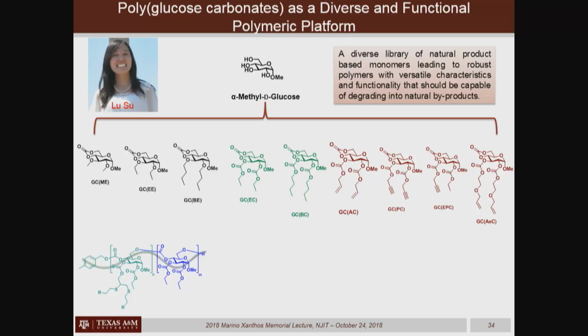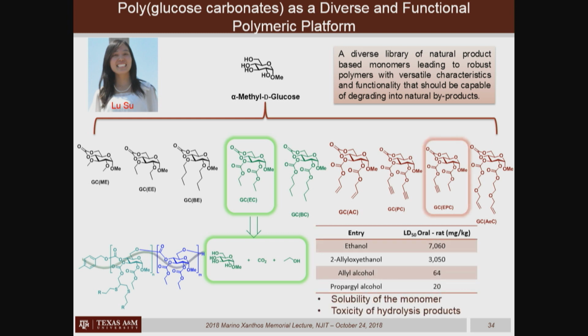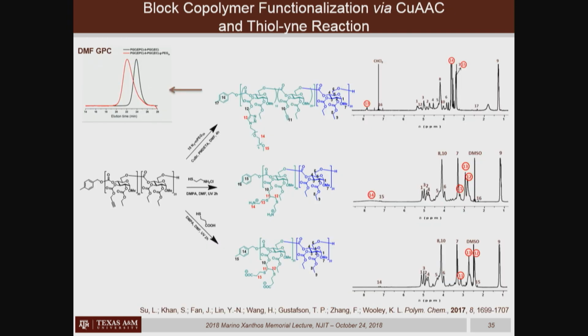And so that was done by Lu Su, and she recognized that Koichiro had been working on just this one monomer, but all of these species have that 6-membered cyclic carbonate, and they just have different things dangling along the side. And those dangling groups are critical to the behavior of the polymers. So 2 of them that she's focused on are this one, where she has ethyl carbonate groups as what are protecting groups, but they're also labile. So this monomer and polymers from it will break down into methyl glucose, which ultimately will lead to glucose, carbon dioxide, and ethanol. And she's also focused on this second monomer, which has not only an ethyl carbonate at what's called the 2 position, but also a propargyl carbonate at the 3 position. So now that brings in side chain functionality. So from one particular block polymer that has, again, the ethyl carbonate protecting groups on this segment of the chain, and then an ethyl and a propargyl carbonate on this end, we can take that triple bond and do chemistry on it.